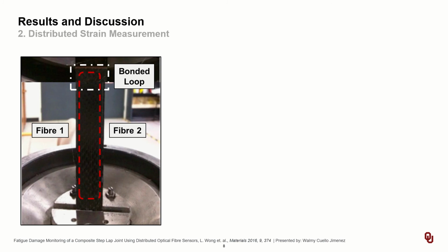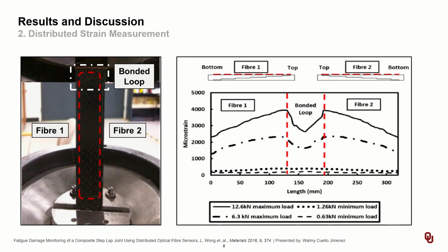The second evaluation consists of monitoring the ability of the system to measure distributed strain across the entire fiber prior to fully diving into the fatigue evaluation. Results show the effect of different loading regimes on distributed strain. 4 key features can be immediately identified.